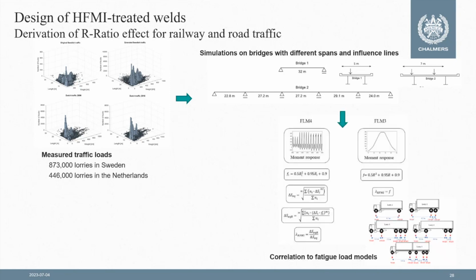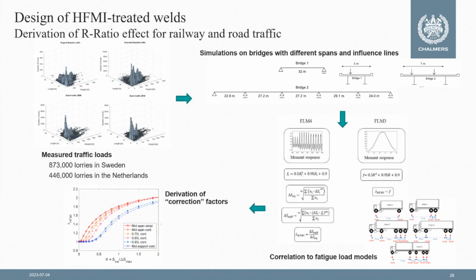And then this was used together with fatigue load models, both fatigue load models 3 and 4, in order to correlate real load effects to the load effects that are coming from the load models that are used by designers. And the result of this is some kind of derivation of a correction factor. And this correction factor, which is called here lambda HFMI, is then used to reflect or describe the variation of R ratio from real traffic on bridges in correlation to the traffic load model that is used by the designer.